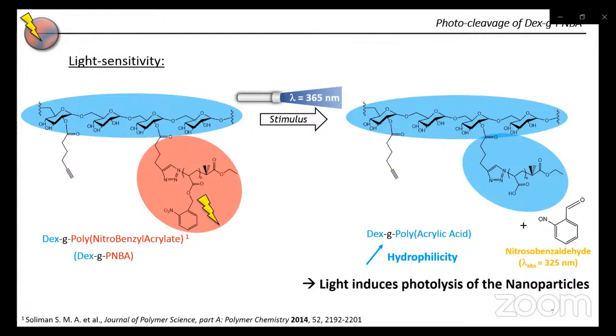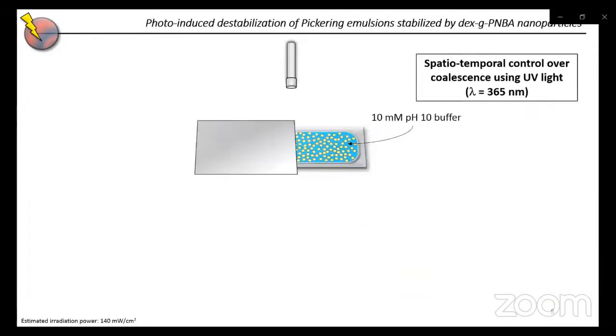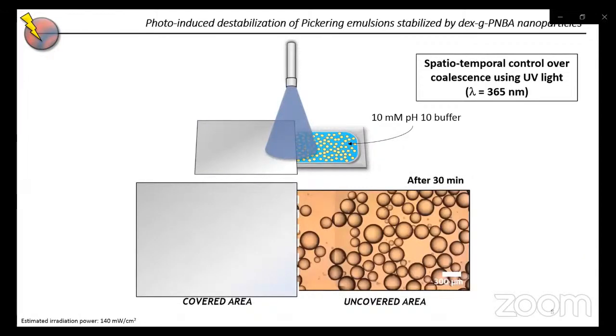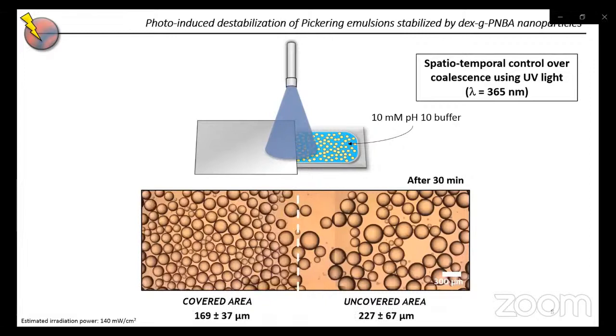So we verified this by studying various parameters, intensity, time, to verify that our nanoparticles can be degraded thanks to UV light. And then we performed some destabilization steps in the Pickering emulsion system. So we covered one part of the emulsion and we irradiated the other part. What we were able to see after 30 minutes is that the covered area did not experience coalescence events, while the uncovered area showed a higher size of the droplets, which shows that coalescence events occurred.